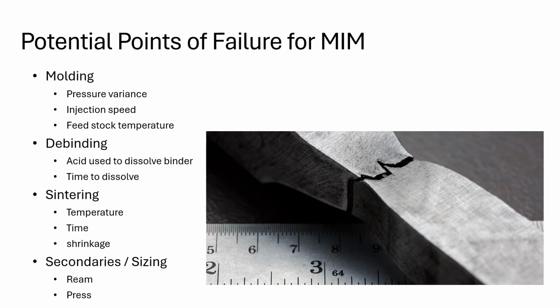Now, MIM has a lot more potential points of failure compared to press metals. During molding, pressure variance, injection speed changes, and feedstock temperature can all affect the quality of the part. During debinding, you have to figure out the right acid used to dissolve the binder and how much time it takes for the majority of that binder to dissolve. During sintering, you have to determine the temperature at which you place the parts in the furnace, how long you keep them there, and account for the shrinkage that's going to occur to those parts. Additionally, even after sintering, often it requires secondary processes like resizing the parts using a press or re-reaming holes.